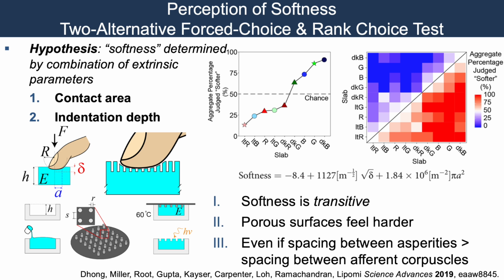And this is true even if the spacing between asperities is greater than the spacing between afferent corpuscles in the skin. This spacing was on the order of 40 microns, which is actually smaller than the distance between your mechanosensory neurons that are responsible for measuring the edges of objects. The reason for that, we believe, is that these porous surfaces produce an inhomogeneous strain field in the skin that makes them feel different, even though the lateral spacing should be too small to feel with your nerve endings. This is some unpublished work that we're pretty excited about.